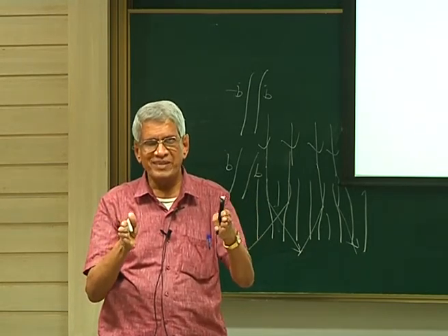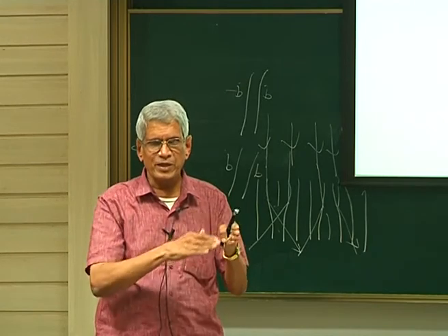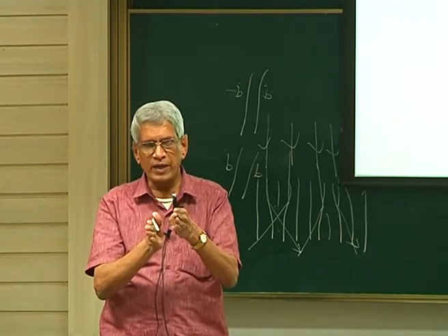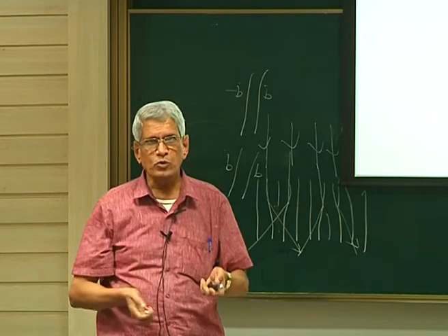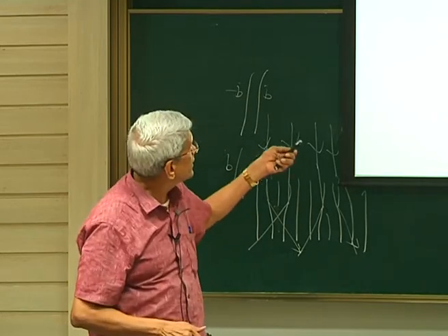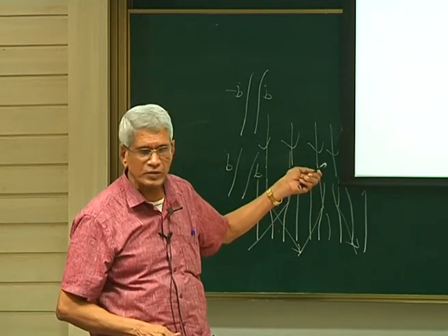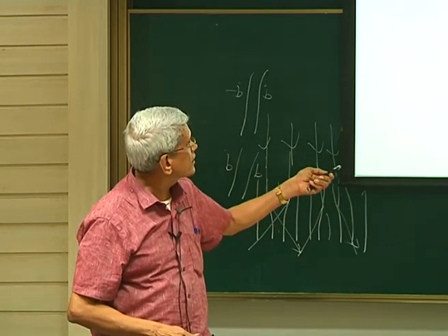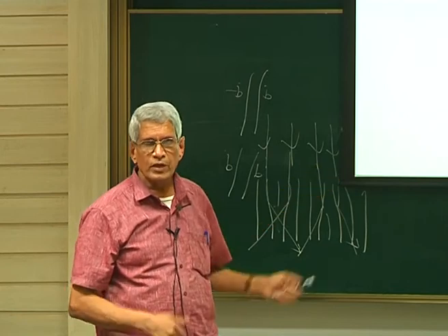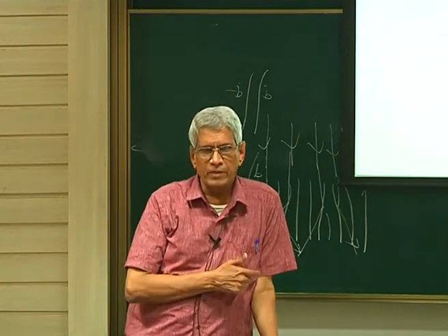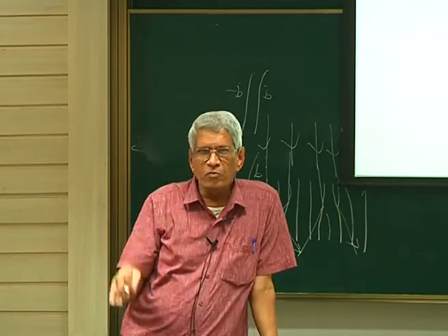When we reverse the G vector, one image will come, another image will come, so the spacing between the dislocations will be different. That is what is being shown. One is G and another is minus G. You see that this looks like two dislocations. If we do a G dot B condition for invisibility, both of them will be invisible.